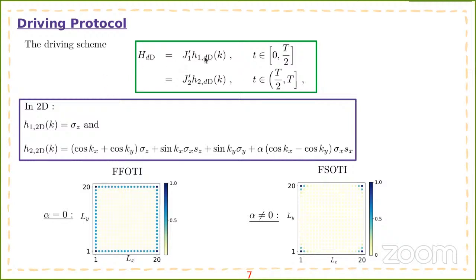So we use a 2-step drive. In the first step, the H1 is basically a onsite mass term, and in the second step, the H2 contains all the momentum dependent terms, like hopping, spin orbit, and one alpha dependent mass term, and this alpha plays an important role in getting the higher order phase. So when alpha is 0, one gets the first order phase, and when alpha is not equal to 0, one can get the second order phase.